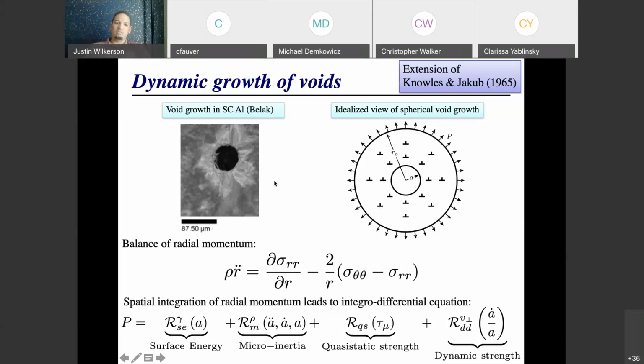So I end up with this really simple integral differential equation that governs the dynamics of voids. On the left-hand side, I have the far field applied pressure, and then on the right-hand side, I have 4 terms. One is associated with the surface energy of the material. This is basically the Laplace pressure, so 2 gamma over a, essentially. This is only going to be important for really small voids.